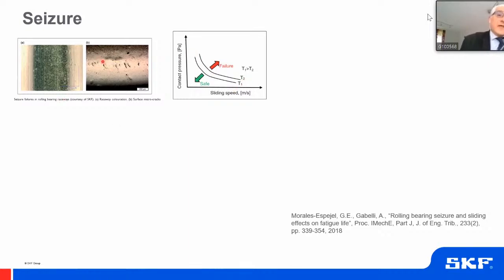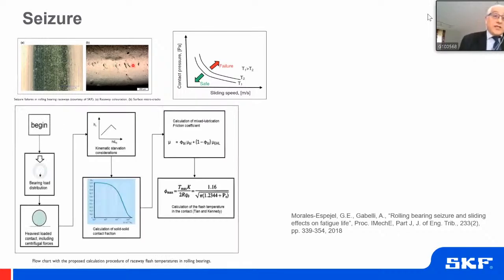In a rolling bearing, you will see the failure starting to appear like this one, with tiny micro cracks here. But if you look into the raceway, you will see that there is discoloration due to the high temperatures. And this is an indication that this is not regular surface distress, but it's actually the beginning of what we call seizure failure mode. The way to model this is relatively simple as well. You isolate the contact with the highest load. You need to model the starvation because we are running at very high speeds here. So starvation is very important.